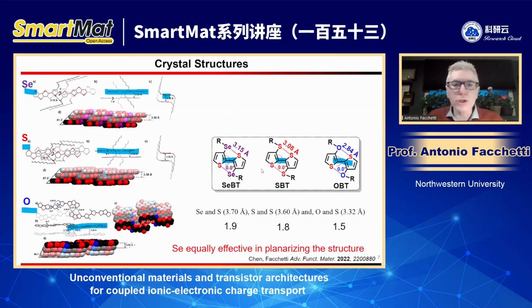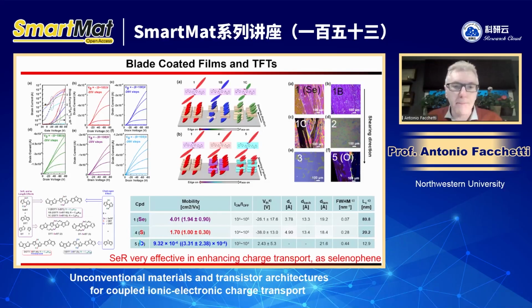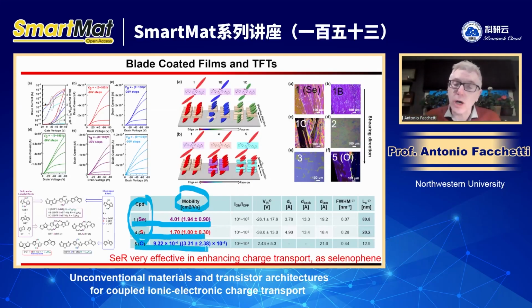I'm not going to go into the detail. I just want to look at the compounds here with the selenium. This is the field effect mobility. And you see here that when you use selenium, the average or the maximum mobility is larger than the sulfur, and much larger than the oxygen. So selenium is also very effective to enhance the charge transport, and you do not have to incorporate it as a selenophene. You can also use a selenoalkyl chain to enhance the charge transport.